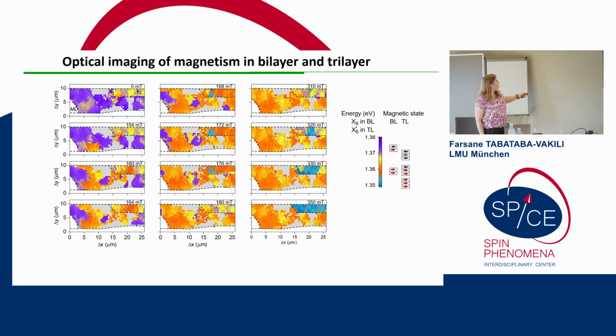We can also nicely see that, so here's the monolayer, close to the monolayer, the spins flip last. And around here, 160 millitesla, the intermediate state in the trilayer starts to nucleate. It becomes fully intermediate, and then here it flips to the other antiferromagnetic state, and by around 300 millitesla, the trilayer starts to become ferromagnetic, and by 300 millitesla, this entire sample region is fully ferromagnetic.